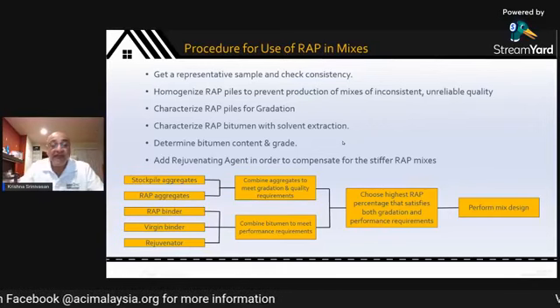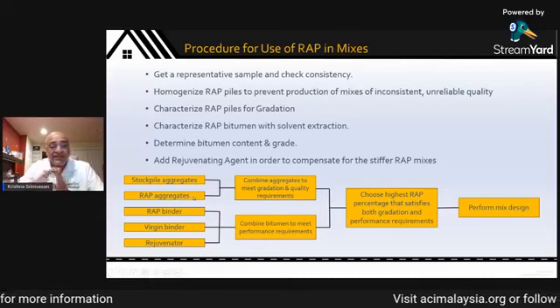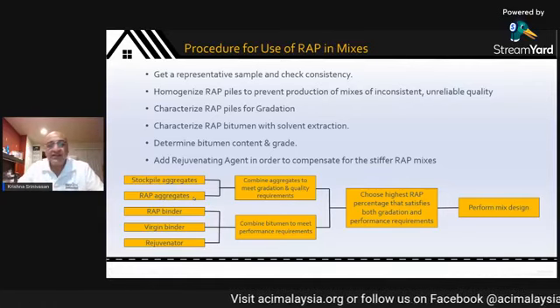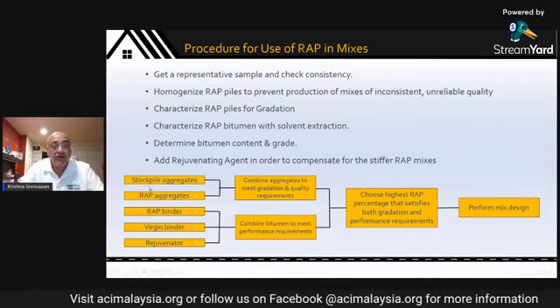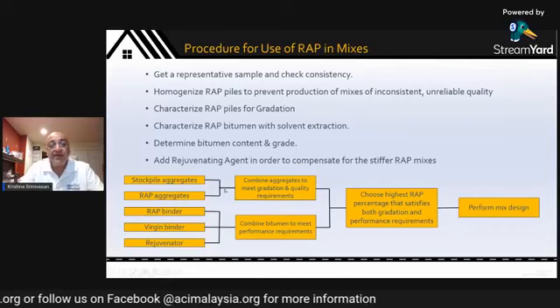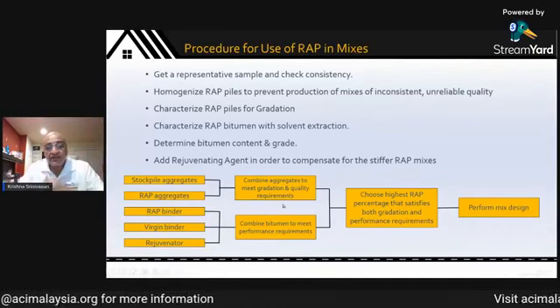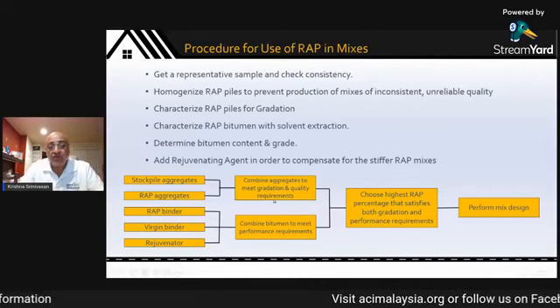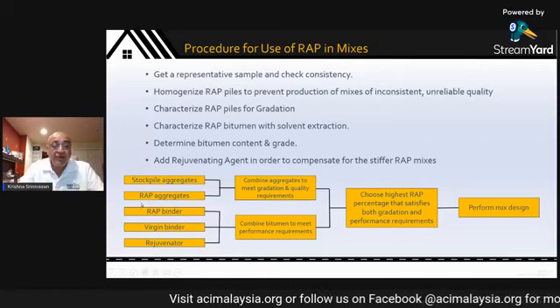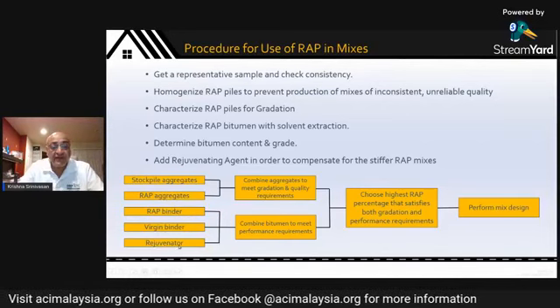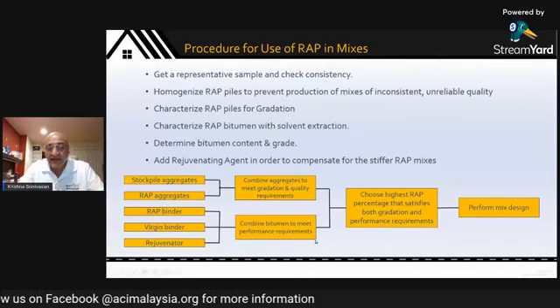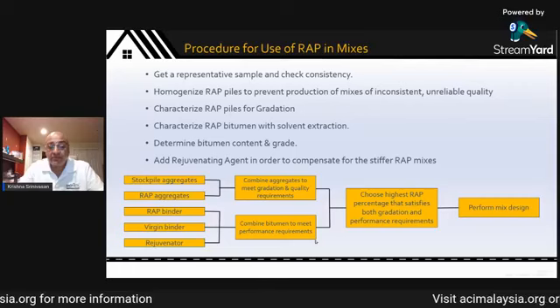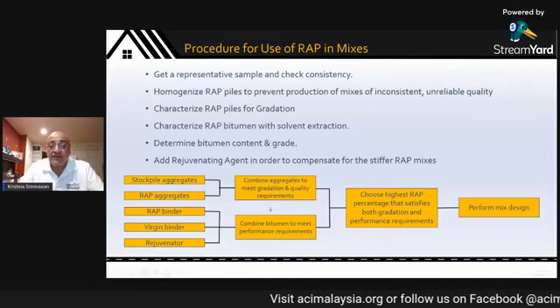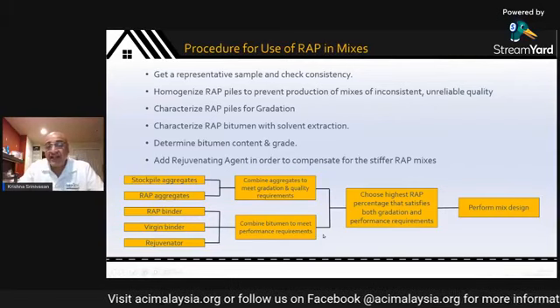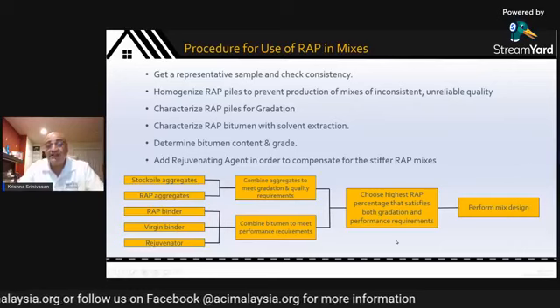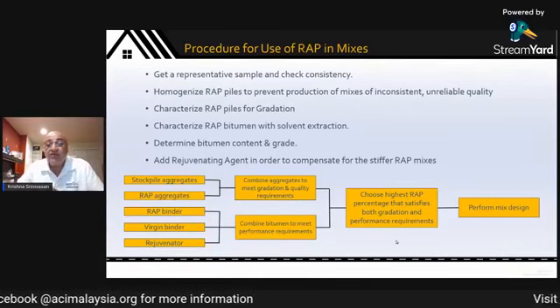And so how does that work in real life? In real life, let's say you've told yourself you want to investigate high RAP mixes. You will have some stockpile aggregates or stockpile rock. You will have some RAP aggregates. You combine them and you add different percentages of stockpile versus RAP to achieve the gradation requirement that your roadway engineer has specified. Likewise, you combine the RAP binder with some virgin binder and some rejuvenator. You combine the bitumen and grade it or measure the properties so as to meet your performance requirements. Now, you do 2 or 3 of these kinds of mixes, and now you are ready to select the highest RAP percentage that satisfies both your gradation requirement and your performance requirement.